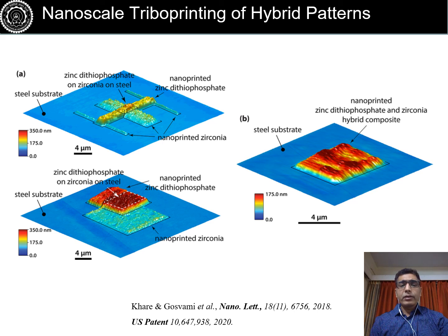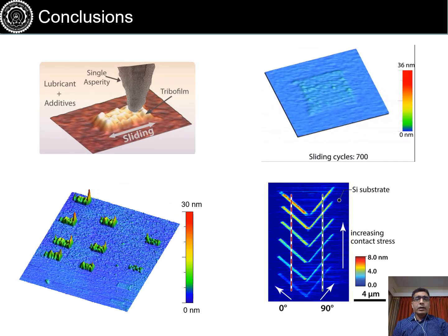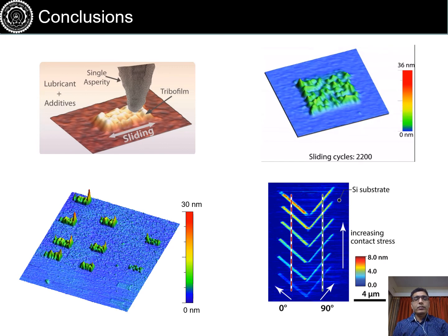using this technique, where we now have the ability to control nanoscale chemical reactions in a very controlled manner, in a very well defined region of interest. And now we are going to try to look for application for these kind of coatings. So in conclusion, I have demonstrated AFM based approach for liquid experiments, where we can have sliding of the probe which can trigger chemical reaction, and that reactions can be monitored in situ, and we can very systematically look at role of various parameters such as contact pressure or temperature, and we can have these reactions to make novel structures, nanostructures or patterns, which can be utilized for a variety of applications.